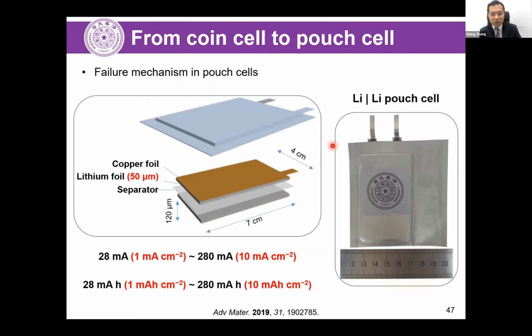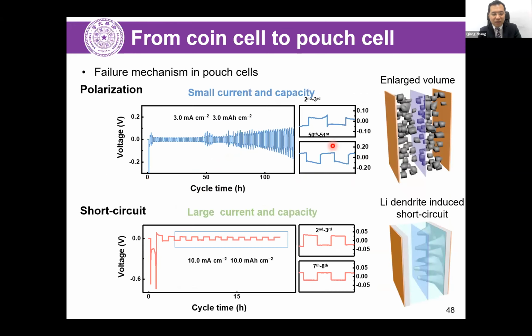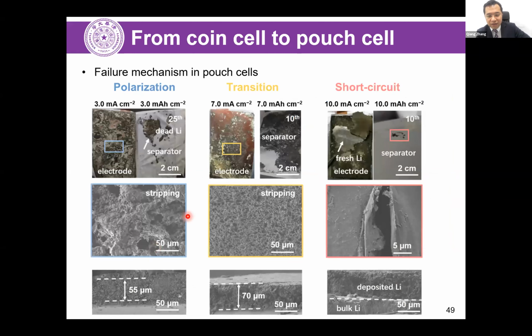We try to probe the charging and discharging behavior of this pouch cell, and it is found that once the capacity and the current density increase gradually, the interface is not stable, and there is a lot of evolution in the structure of the lithium metal anode. Well, if we apply too large a current density, a short circuit is directly observed, which is also confirmed by the observation of a lot of lithium metal residues, where the lithium dendrites penetrate through the separator and induce cell death.